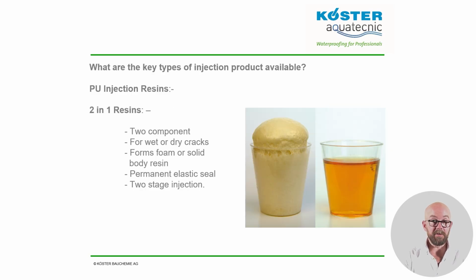2-in-1 resins are very versatile. They are a 2-component polyurethane, but work in a very interesting way. As soon as you mix the part A and B together, the reaction has already started. If you just left that mixture on its own, it would cure to form an elastic solid body resin, as shown on the right. This would be ideal for injecting into dry cracks to achieve a permanently elastic seal. However, if you introduce the freshly mixed material to water or dampness, it will react to make a foaming polyurethane.